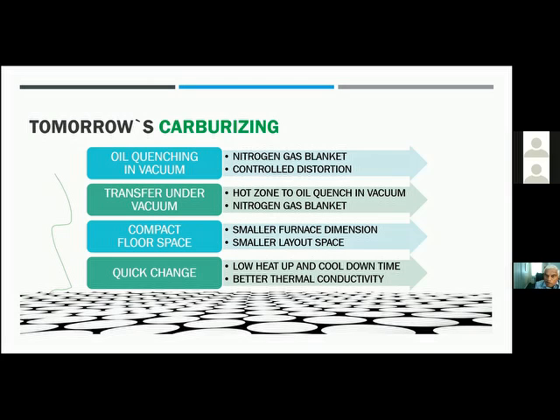It is difficult to assume that there will be no distortion by laws of physics or heat transfer, because you're heating something to such high temperatures and then quenching it. The very process of quenching means there's going to be differential temperature on the surface and the core, and that will bring distortion. The difference between quenching in these systems and in conventional systems is that the quench patterns can be set so that the distortion levels can be repeated. And when you can repeat a distortion level, you can adjust your soft machining so that you can counter the predictable distortions. So you end up having virtually no distortions when you finish, and you probably don't need a post-treatment machine, no hard machine, which is a big advantage. But this is not something that will happen automatically.